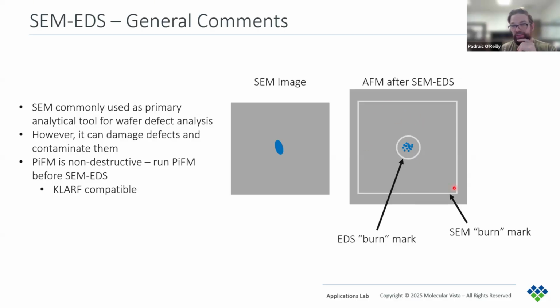But we usually see these square burn marks around the SEM scan area, but we also see circular EDS marks around the defect. Then, due to the higher electron beam power used for EDS, we commonly find the defects ablated into smaller particles, and in some cases, the defects are completely gone. So as you move towards smaller defects, it's more likely that the EDX is going to remove them completely.